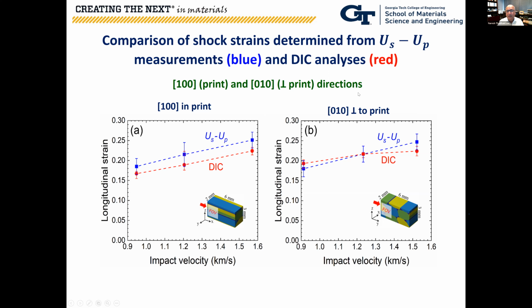And then when you go to the 0-1-0 direction, as we saw in the previous picture, the deviation is much less. So the only difference, I think, in terms of the effect of print orientation is really coming from the local strain, but the bulk properties—the bulk shock compression response—is essentially identical.